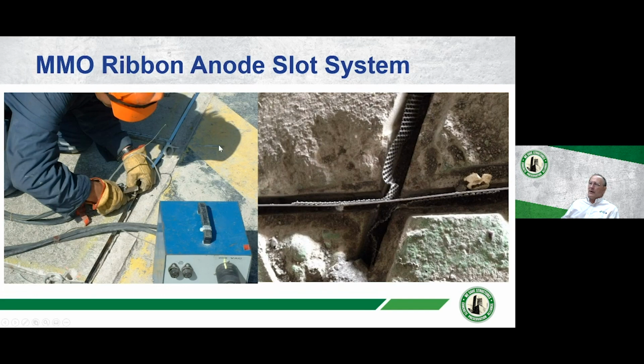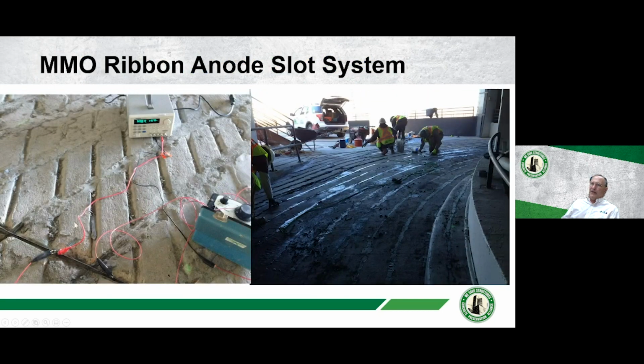Then we installed our ribbon and conductor bars. Here's your ribbon being welded to a conductor bar. And then we tested it, checked for shorts. Once everything passed QC, we grouted it in place. Once we had it completely grouted in place, then they came over the entire surface, shot blasted the entire surface, and put a coating over the top of it.